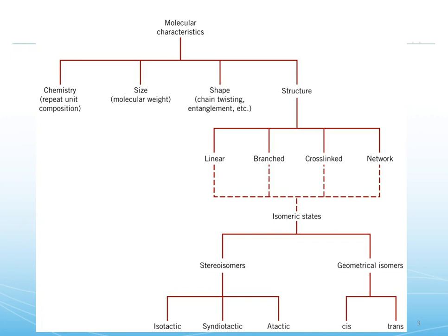If you have a thermoplastic, it could be linear, all one big long chain. It could be branched. You could have a thermoplastic with linear molecules or branched molecules that are linked up at irregular intervals. This is what's done to vulcanized rubber with a sulfur bond. This is called cross-linking. Or you can effectively be cross-linked at every repeat unit, just sort of the ultimate infinite cross-linking. That's called a network polymer. And that's what you get when you react multifunctional polymers like epoxies.